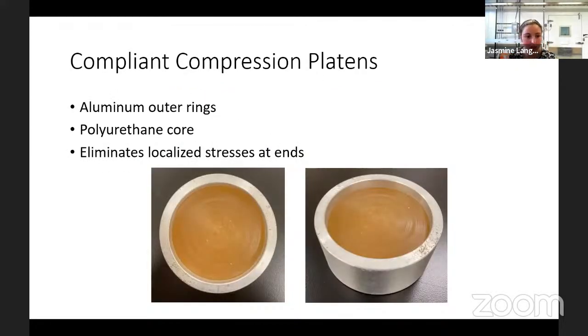So for the compression testing, we made these compression platens. Basically they have aluminum outer rings and a polyurethane core. It allows a place for the ice core to sit so that it doesn't slide out, and the ring confines it. The polyurethane is also soft, so it reduces localized stresses at the ends. With the polyurethane, the ice is more likely to break in the center instead of at the ends, which is ideal for what we're trying to find out.